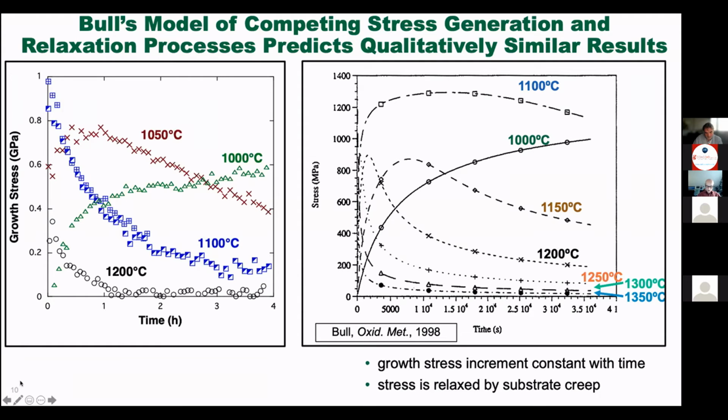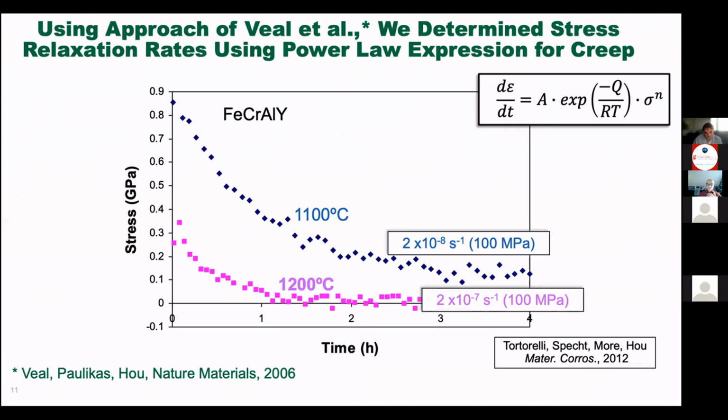However, as I already showed you, we do not have a growth stress that's constant with time. It decreases rapidly with time. And as I will show you over the next few slides, we believe our stress is not relaxed by substrate creep, but by creep in the oxide itself. And that's what I'm showing here.